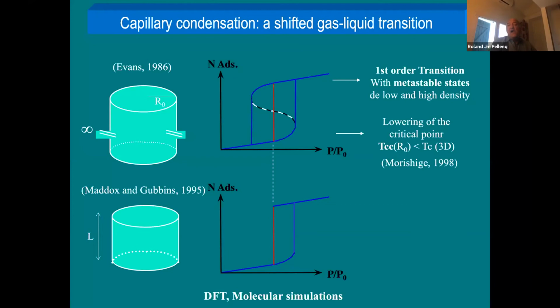If we dig into the physics, work done in the 80s and 90s by Evans, Gubbins and others, using different theoretical approaches and molecular simulations, shows this is a real first-order phase transition. For an infinite tube, you get this sigmoid-type van der Waals equation for the fluid, shifted from the bulk. If you equalize the two areas going up and down—the Maxwell construction—you can localize the equilibrium.